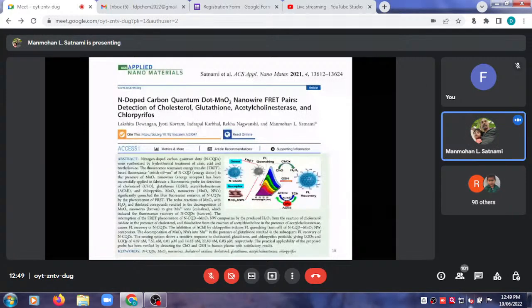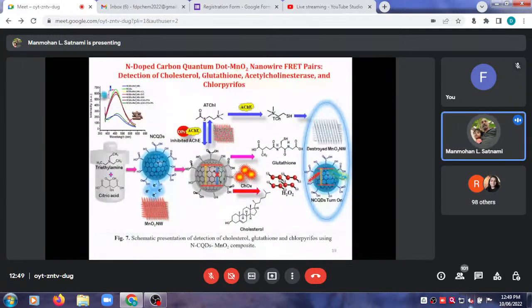So what we did actually, we prepared nitrogen doped carbon quantum dot and manganese oxide nanowire, and we used these nitrogen doped carbon quantum dot and MnO2 nanowires as a FRET pair for detection of cholesterol, glutathione. You know it, this is a very good antioxidant. Acetylcholinesterase enzyme we determined, and we detected chlorpyrifos, which is an organophosphorus pesticide. Okay, so how did we hypothesize? Actually, all the teachers and most of us, maybe we are engaged in research work.